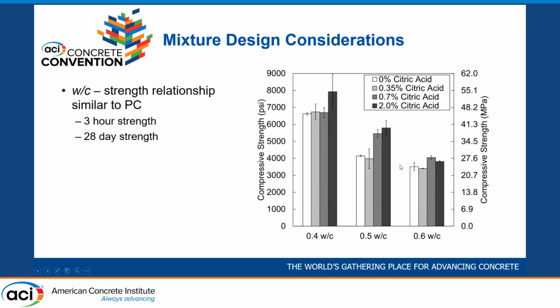One other point I should make is these mixtures that have 0% citric acid, our strengths were quite good, but these were very hard to consolidate. As you saw from the slump figure, it's hard to get a good slump out of mixtures with no citric acid. So again, I probably would not recommend doing these mixtures without any set retarder.